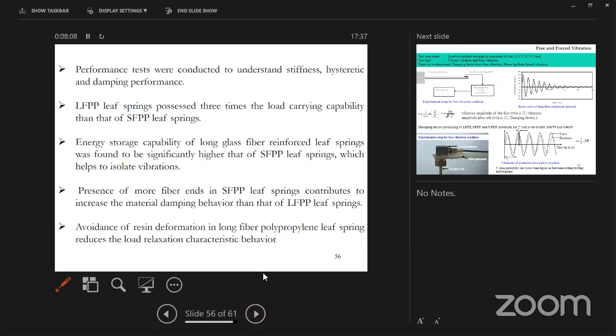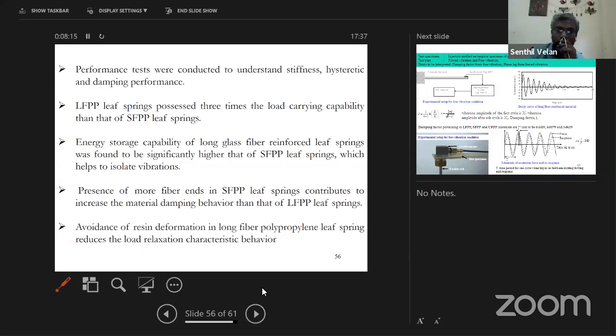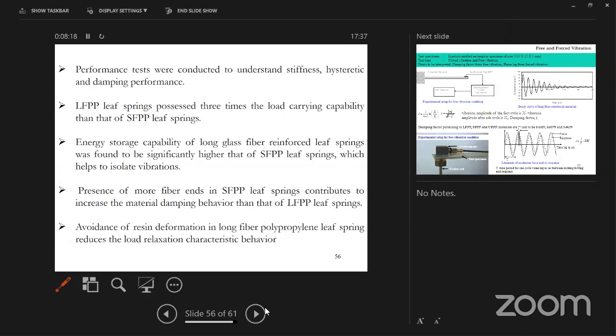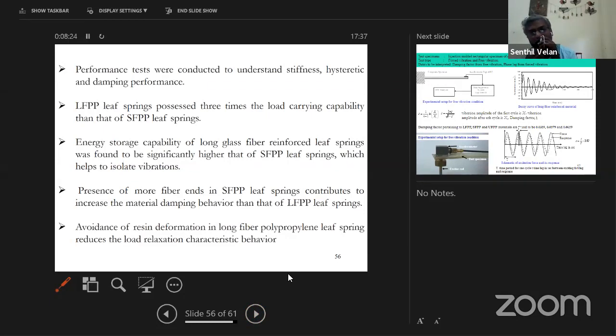The other question is, which is the most frequent failure form in polymer gears? Failure is mostly thermomechanical failure, because unlike elastic material, where we don't go up to such a high temperature, here, polymer being a polymer material, there is heat generation, as we have just seen in the hysteresis. That is internal heat generation because of molecular collision. So when the component is subjected to fatigue load, structural plus thermal also comes into it. So it is mostly thermomechanical behavior, and we have to concentrate more on these thermomechanical failure aspects.